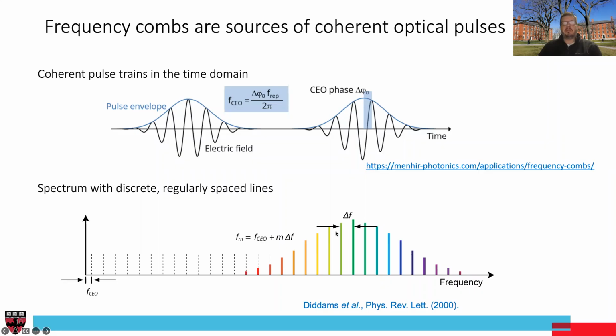The big deal in the frequency comb business is stabilizing the comb, which means stabilizing, locking the pulse envelope with the optical signal itself. And for that, typically what's needed is to detect this carrier envelope offset frequency, f_CEO, which actually requires second order nonlinearity like the one provided by lithium niobate. So the goal of our research is actually to eventually provide a complete solution to stable, broad frequency combs that could also be very small and portable.